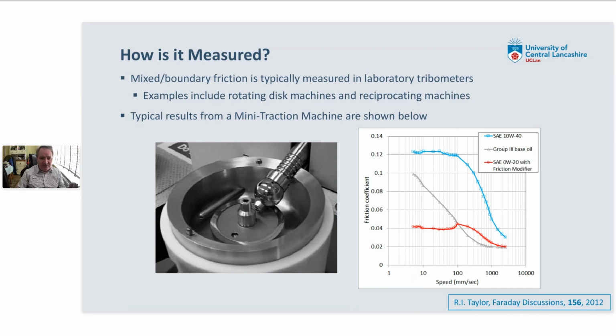And so we've got some results. Typical results are shown here for a 10W40 engine lubricant. This lubricant is the blue line in this graph. This particular lubricant will have quite a lot of anti-wear additive in, and that tends to give you quite a high friction coefficient of about 0.12, and it stays high up until about 100 or 200 millimeters per second. Then we see it dropping off as we go into the mixed